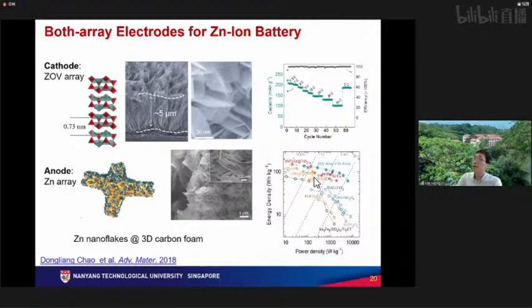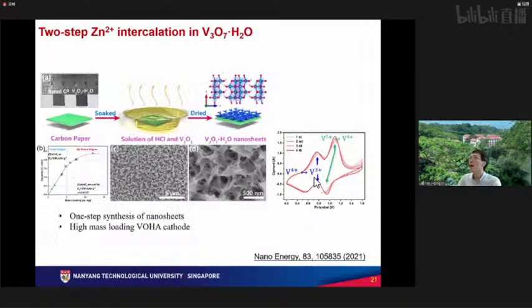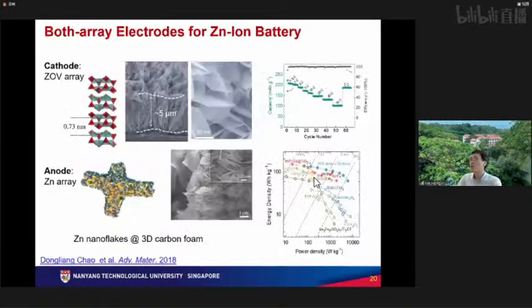mass loading. The mass loading can be even higher compared to the dense 2-dimensional films. But more importantly, it can increase the DOD, depth of discharge, and have a better utilization ratio of zinc. So we make a quasi-solid state zinc-ion battery based on this array structure on both cathode and anode, and find that the energy density at that time can outperform a lot of other full batteries by including both cathode and anode mass. Also it can go to very high rates because of the array structures.